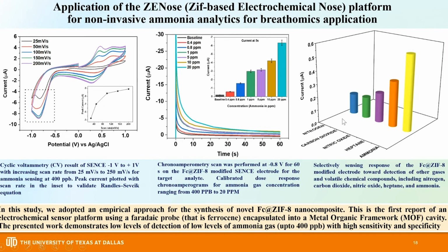And the cross-reactivity was performed in the presence of nitrogen, CO2, nitric oxide, heptane, and ammonia. As we can see, the sensor showed the highest sensing response for ammonia. So in this study, we actually used an empirical synthesis approach. We characterized the synthesized materials and showed the successful synthesis, which was then further used for the application.